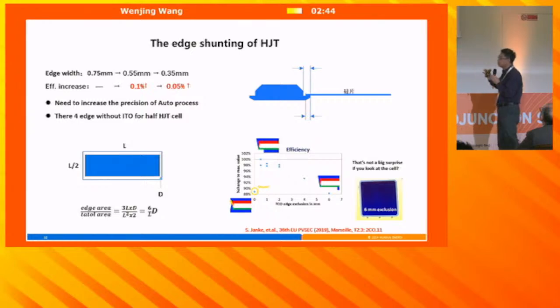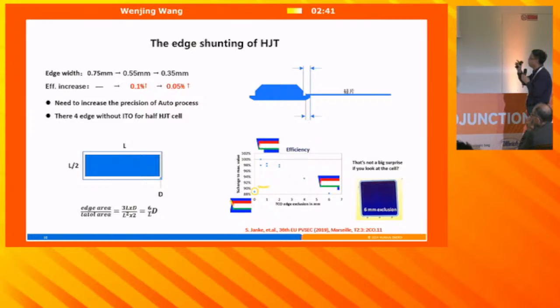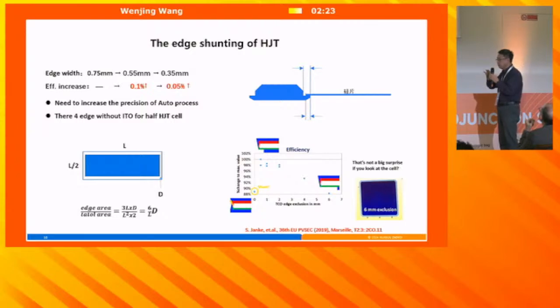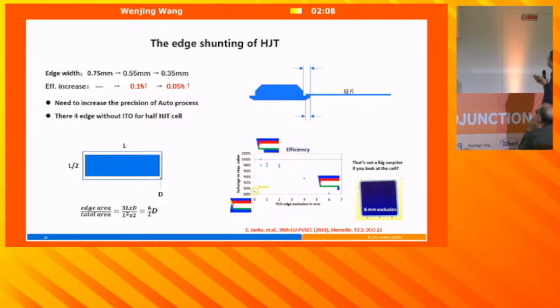But we can further decrease the width of this no-ITO area to 0.35 millimeter. The efficiency can further increase by 0.05%. But it needs very precise automation. Sometimes it is too narrow for the holder, and some wafers can go down.